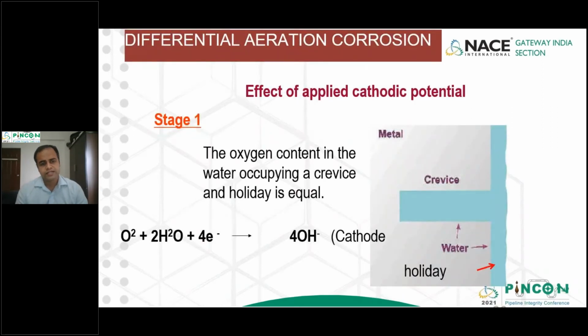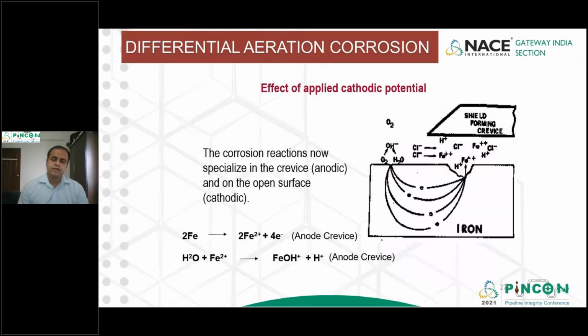Now, the oxygen content in the water occupying a crevice and holiday is equal because of the reaction which is driven here, that is O2 + 2H2O + 4e- gives you 4OH-. This is the alkaline solution which is created. Now, the crevice and the holiday are having equivalent concentration of oxygen. In stage 2, what happens is the corrosion reactions now start. They specialize mostly in the anodic area, which is the crevice in this diagram, which you can see, and on the cathodic area also. Now, in the cathodic area, the reactions are more dominant compared to the anodic area.